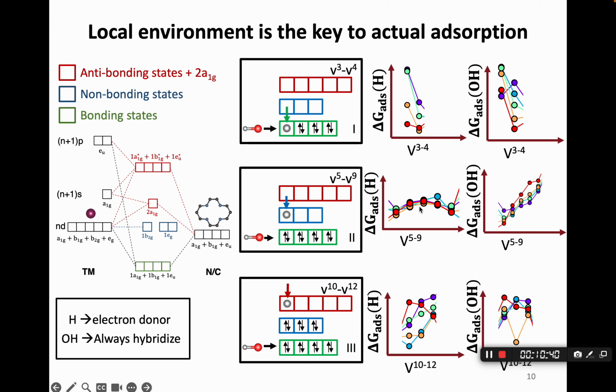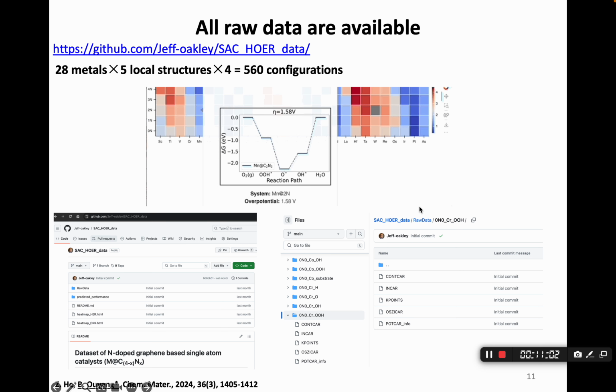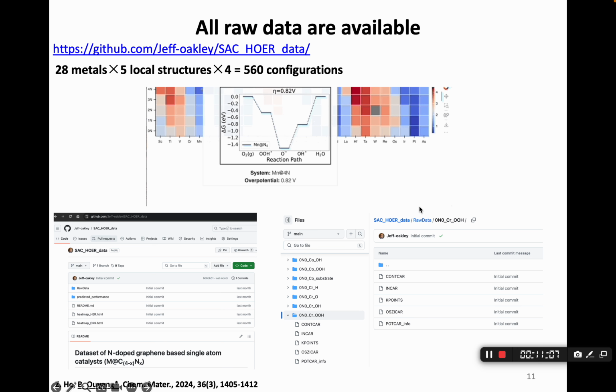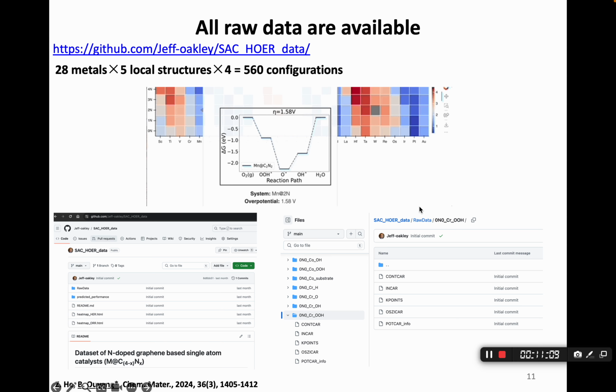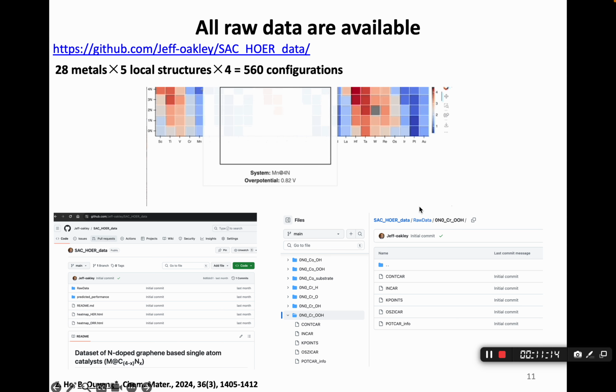Okay, so in both cases, the adsorption energy pretty much depends on the local hybridization, so it's very system dependent. This is some kind of qualitative trend that we can observe for single atom catalysis, but honestly, we cannot go much further than that. There's no way for us to really quantify the adsorption energy with a clear and accurate enough model. And this does not necessarily mean that there's no way of quantifying that.